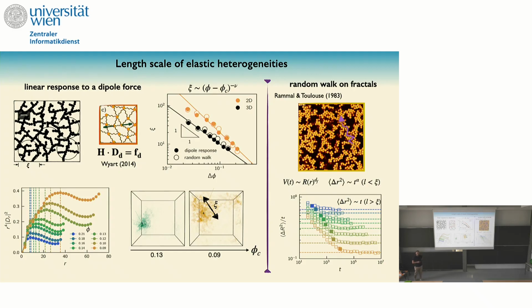With elasticity, you don't have a length scale, it's just a power law. Yes, but you have a power law in the far field that gets you the linear elasticity, and you have another power law in the close field that deviates from what you expect from linear elasticity. In other words, the displacement field squared goes as 1 over r to the power of 4. This is for linear elasticity, but below that you have r to the power of -1. So you have a crossover from 1 divided by r to 1 divided by r to the fourth, and you define this length scale as the crossover between both.